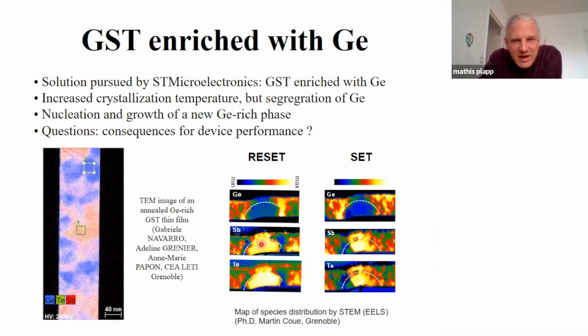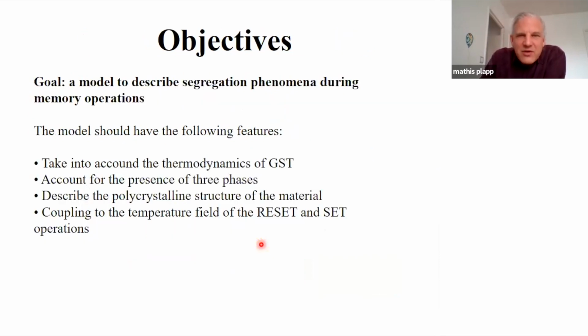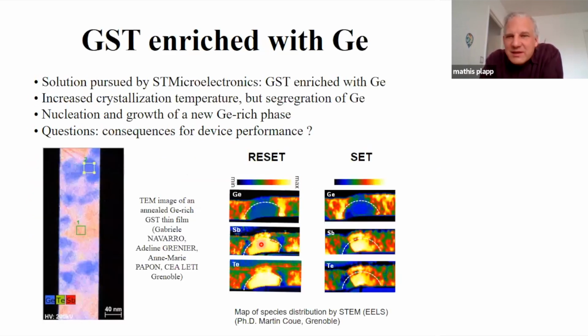Okay. So we said, well, this is very challenging because the model should be able to do numerous things. It should be able to do GST or something that is like GST, so they have the right thermodynamics. It must have three phases: germanium rich, GST, and the amorphous. It should, if possible, also describe the grain structure of the material. And we should be able to couple this to the temperature field that is created by the heating in the memory point.